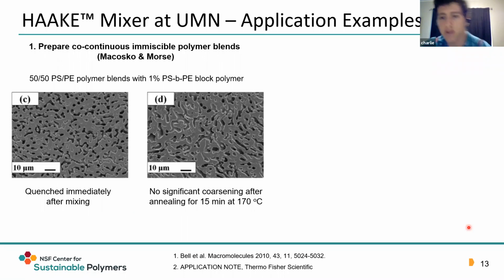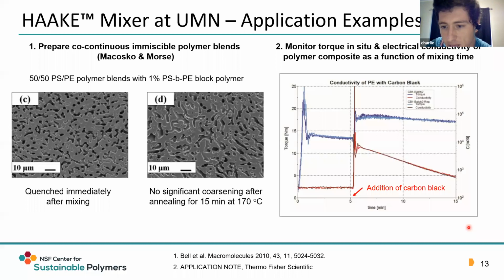An example of research that used the HAAKE™ at the U of M was done by the Macosko and Morse group, and they used it to prepare polymer blends, co-continuous blends specifically. They added a block copolymer which stabilized the blend, and you could see the results here.